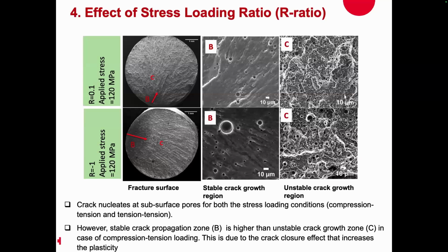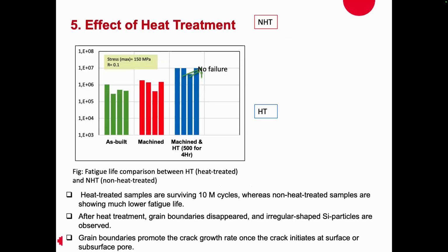The stable crack propagation zone in B is higher than the unstable crack propagation zone C in the case of compression tension loading. And this is due to the crack closure effect that increases the plasticity. And this difference between the stable and unstable crack growth zone between tension and compression causes the lower fatigue life for tension loading as well, which we need to take into account for AM.